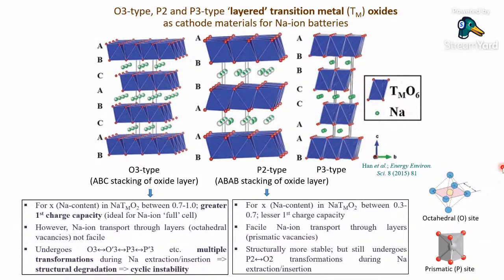So now, when we talk about the structure of the layered transition metal oxide cathode materials for sodium-ion cells, typically three types of structures can be used. Now, when we talked about lithium cobalt oxide and lithium NMC, they had this particular O3 type of structure, where O indicates that the sodium ion or the lithium ion resides in the octahedral site, whereas 3 indicates the number of types of oxygen stacking in a given unit cell. So the structure types can be denoted as O3 or P2, where P is a prismatic site where the sodium ion can reside, P3, and so on.